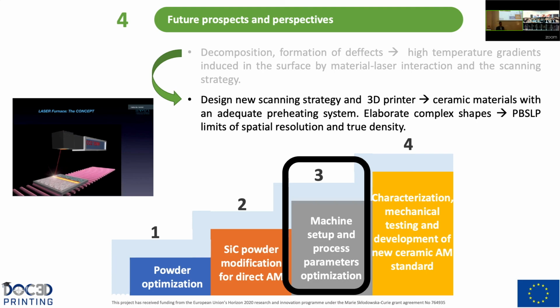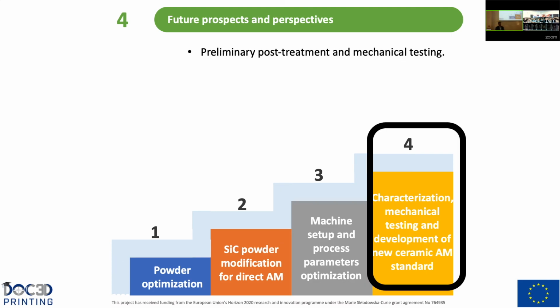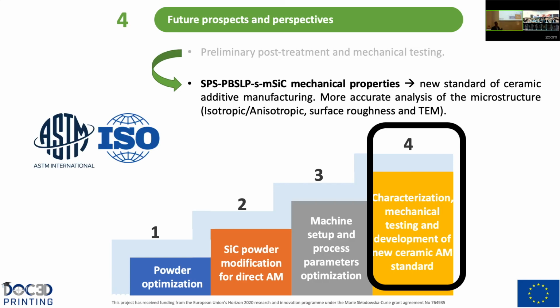And finally, regarding the characterization and mechanical testing, we performed just some preliminary post-treatment and mechanical testing. So here, of course, we need to measure the mechanical properties of the surface modified silicon carbide after the additive manufacturing process and spark plasma sintering. And we should create a new standard of ceramic additive manufacturing because at present we have no information. And moreover, we should perform more accurate analysis of the microstructure, such as to know if we have an isotropic or anisotropic part, to study the surface roughness and transmission electron microscopy.